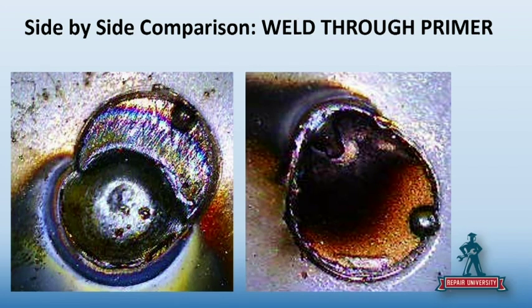So that's just the very first pull of the arc, and you can see you're off to a good start. Now, if you have coatings in the weld zone, like we have over here, first of all, you can see all the soot. Contamination, you're going to have contaminated porous welds. That's pretty obvious from the picture. Which is a weaker weld. Right, but now you can see that from the first pull, it didn't even jump onto the metal, it kind of just flew off, right? That's your spatter that you're looking at, right? So you didn't get any fusion.